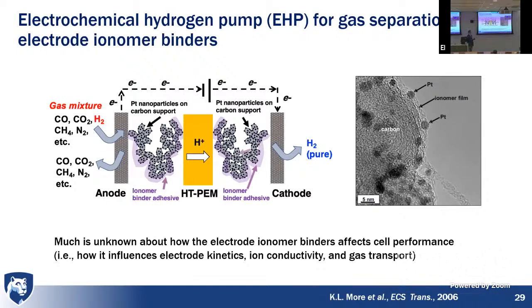But we need to process this into a freestanding porous electrode, or an electrode that's appended to a membrane or a gas diffusion layer. And to hold those particles together, you need an adhesive, like a glue. And that adhesive, a glue, oftentimes in the low temperature case, is the same chemistry as this membrane. And it will coat the surface like this, right? And this coating on the surface will have a real impact to the electrochemical reactivity of the particles. And really, much is unknown about how this binder affects cell performance. How does it affect conductivity under thin film confinement?